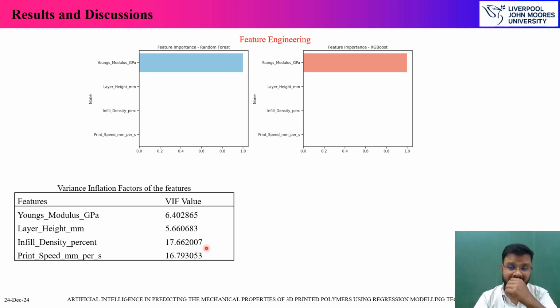But however, from the subject matter knowledge, it is very evident that the density of a part plays a vital role. For example, let's say that this is the solid panel what we see here. This solid panel, it becomes very difficult for us to bend it. But whereas if the same solid panel is replaced with a zigzag pattern or any particular pattern which is slightly hollow, in that case it easily deforms. So clearly, even though the VIF value is maximum at 17.66 for infill density, from the subject knowledge it is not recommended for this feature to be eliminated.